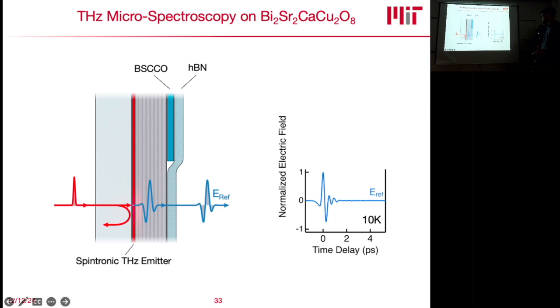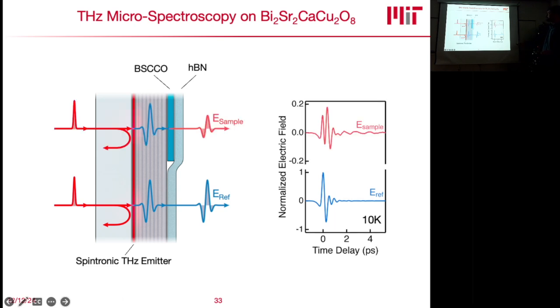We get our reference measurement, and we can now move our focus of our pump into our sample and do a terahertz transmission experiment through the sample. And then we can compare these two things. What you can immediately see is that the amplitude is dramatically reduced because it's a superconductor. It's basically a very good metal, so it should screen terahertz. But we also see these coherent oscillations, which already hint at something that has what people call a finite mass or finite restoring force, so some sort of plasmonic resonance.